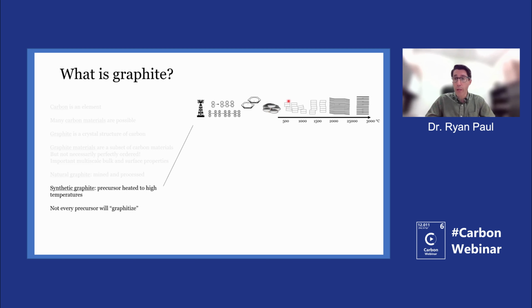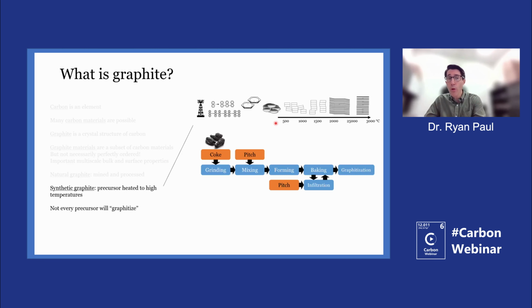You will get good ordering of these stacks of aromatic compounds, and as you heat and heat, and as this cartoon suggests, you can essentially get to a very well-ordered graphite-like material. Usually not as ordered and as perfect as natural graphite, but can be very close, although the morphology is a bit different. But not every precursor will graphitize. And by controlling the precursor, the actual chemistry and molecular distribution in the precursor, you can get to a variety of almost graphite materials, or you can pick some materials that even at very high temperatures will not convert to this graphite structure.